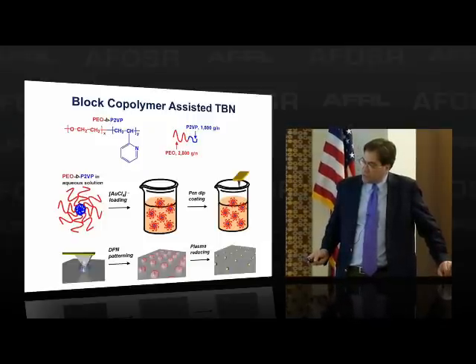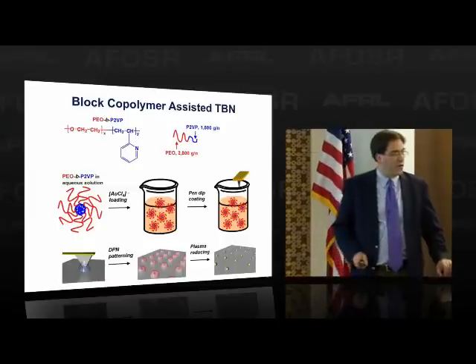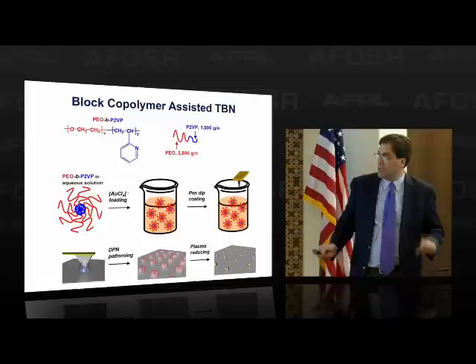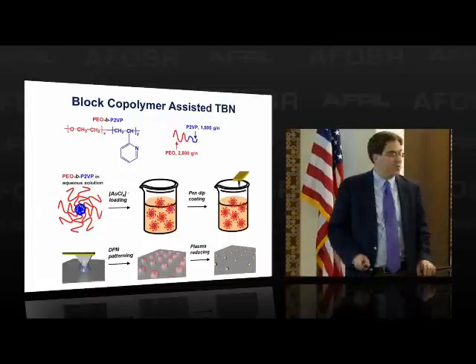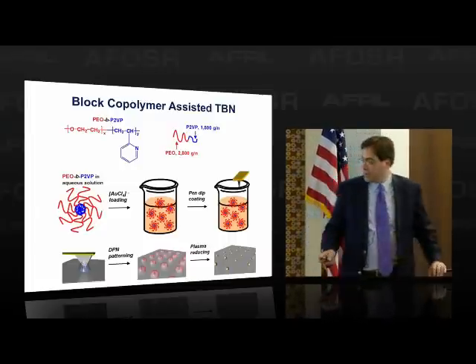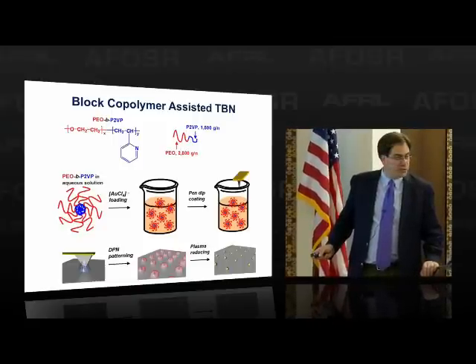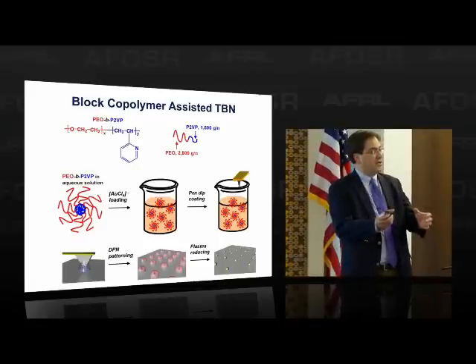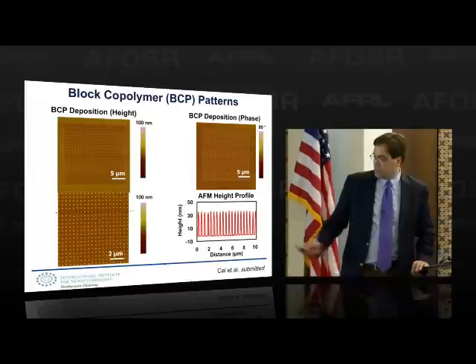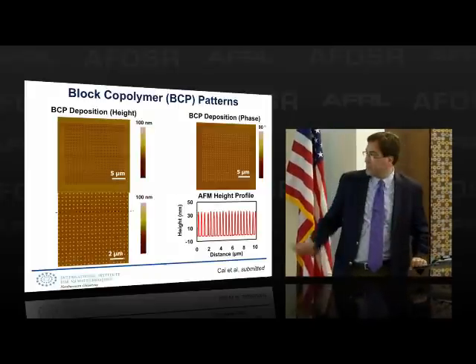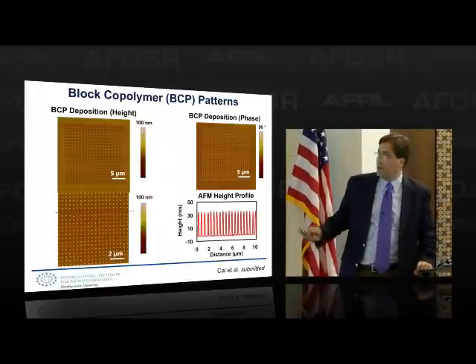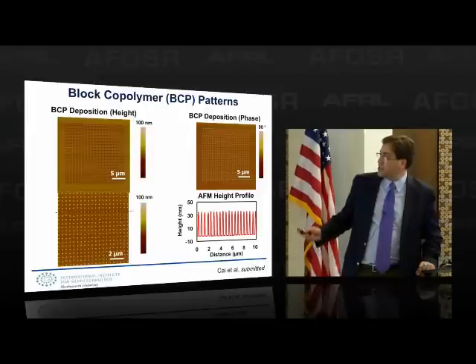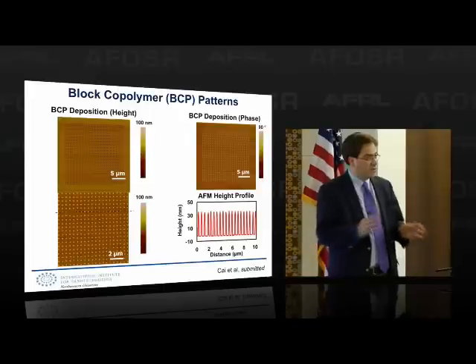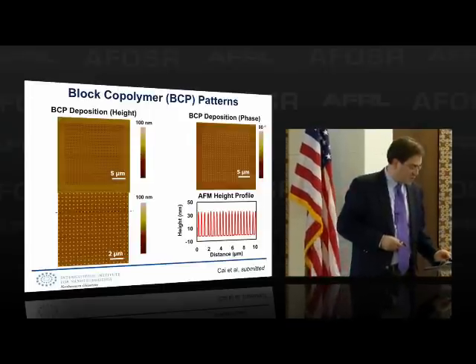And what this does for us, it creates features, polymer features, where the volume of the feature precisely controls the number of atoms, metal atoms, that can be used in a subsequent synthetic step. And so if all things work well, the idea is we're going to reduce with a plasma. Gold will go to gold 0, begin to cluster, and form nanocrystals where the size of the crystal depends upon the polymer volume. Here you can see the uniformity is pretty remarkable. And what's important here is not just the diameter of the features, but look at the height. If that doesn't work, then none of this works. So being able to control all these parameters is what's critical.